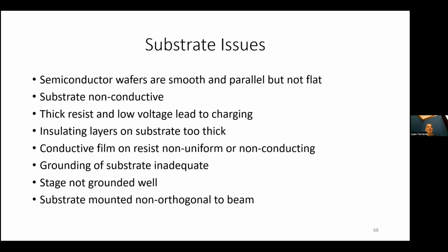If we have non-conductive substrates like silicon nitride or something, that's a problem because it's an electron, it's not a photon. That electron wants to go where the field lines are, not in a straight line like a photon does. So as we charge up the substrate, we'll lose focus. The same thing can happen depending on your voltage and your insulating layers. Many people will have 285 nanometers of silicon oxide on it. They're working with graphene. If we work at 5 kV, some of those electrons are going to get stuck in that oxide. If we work at 100 kV, virtually all those electrons are going to go through the oxide into the substrate, get carried away to ground. We can fix that by putting a conductive film on top of our substrate and then grounding that conductive film so as the electron comes down, it just sees ground potential, it doesn't get deflected.